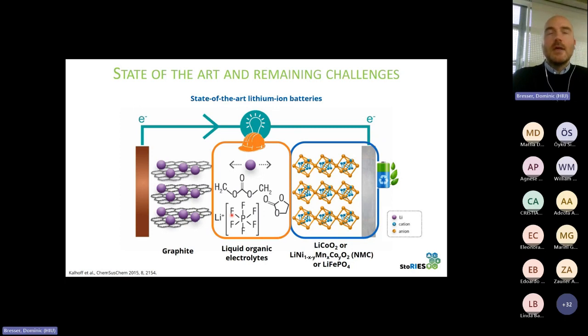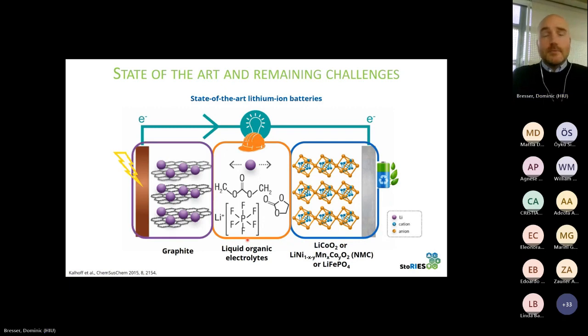When talking about safety, you might easily imagine that these liquid organic solvents are very flammable. So it's largely about the electrolyte, and it's not only about the flammability of the solvents, but also about the reactivity of LiPF6, for instance, in combination with water forming HF, which is not only highly corrosive, but also generally toxic. And then when talking about performance, especially fast charging, then it's especially about the negative electrode, so about the graphite. And energy density as well, but that's apparently the sum of everything, as you've seen just a few slides ago.